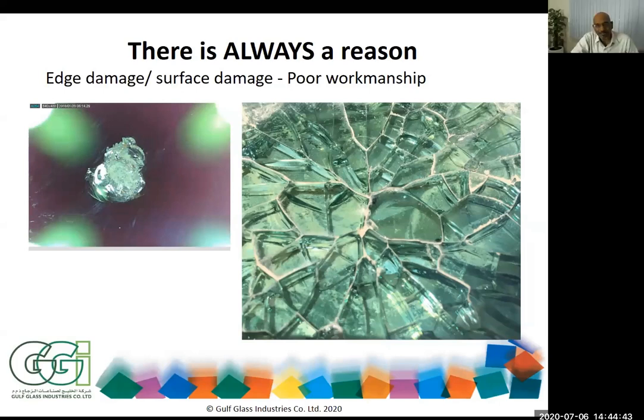Not instantly glass breakages, but after a few months. And this was during the summer months in the Middle East. It gets too hot, and you could see that we had 400 units of breakages just because of the surface damage. So this is another reason where we have surface damage causing glass breakages.